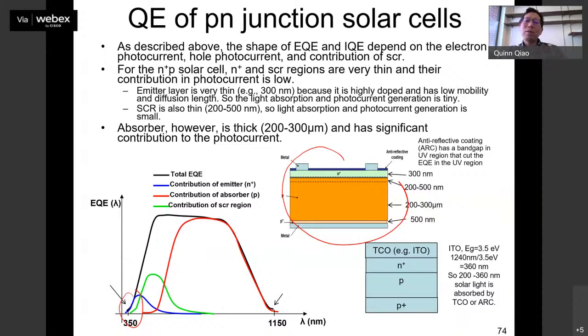You measure the absorption coefficients at the different wavelengths, which wavelengths will go deeper into the materials, right? And that means absorption at the surface is not strong. You don't absorb a lot of sunlight, you will not generate a lot of charge there, right? And then when you get deeper, you generate more there, and then you can use that to study the bulk properties. And then you can use different wavelengths that absorb more on the surface to study the surface or interface properties. Or you can also adjust your light intensity, right?